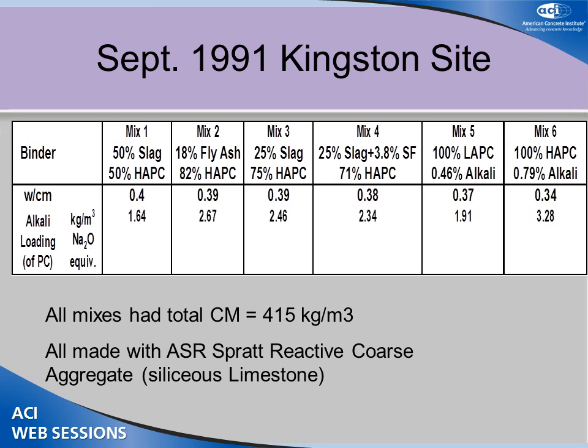There were 6 mixes, as I mentioned. I've got them in the order we placed them. We had a high-alkali Portland cement, which we then used with 50% blast furnace slag. We used one that had 18% fly ash. We didn't pick 18 because it was a good number to use. We picked it because that's how much fly ash we had available at the ready mix plant in Kingston, Ontario that day. We would have used more because we knew that 18% wasn't sufficient, and I'll come back to that.